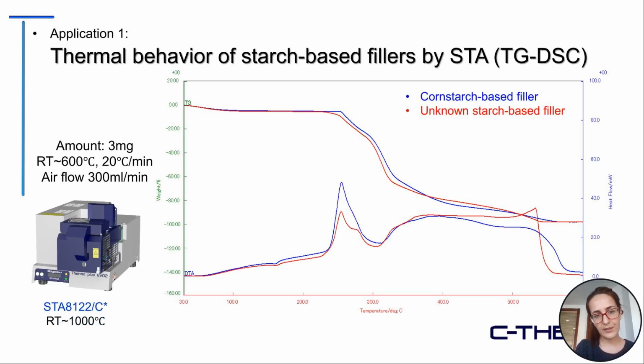In order to have a better idea about the thermograms of these two kinds of starch, we plotted all the curves together. As you can see, the blue curve is denoted to the corn starch-based filler, and the red curve is related to the unknown starch-based filler. In the TGA, you cannot see a lot of change between the two samples. But in the DTA, you can see some small changes during the exothermic peak and also the endothermic peak, which is related to the difference in the composition and crystalline structure of these two samples.